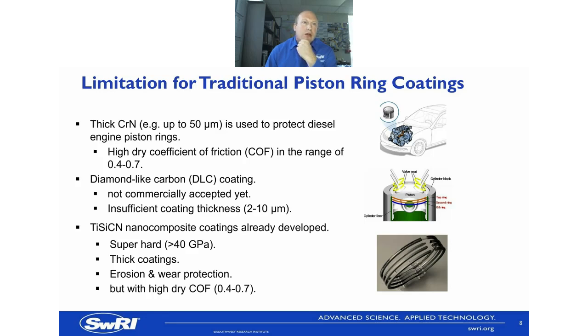So by targeting the piston rings, what we did was a thick coat of CrN. Sorry, I apologize. No, we didn't do a thick coat of CrN. What we're looking at here is the limitations in 2013. Obviously, some of this has developed since then, but in 2013, there were limitations for traditional piston ring coatings. They used CrN coatings of up to about 50 microns in diesel engines. That's okay in diesel engines, gasoline's not so good, but it has a high dry coefficient of friction, and so that's obviously not great for fuel economy. DLC coatings weren't really commercially accepted in about 2013, and there was really insufficient coating thicknesses at that time.